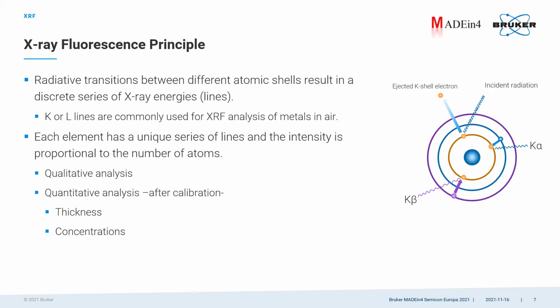This is a brief refresher on what X-ray fluorescence is. So we hit the sample with a primary X-ray beam. By doing this, it's possible that electrons from the inner shells are knocked out, and this will leave a hole in the electron shell, which is then immediately filled by an electron from a higher shell. And this jump creates a photon with a specific energy. Filling this void with an electron from the L shell generates a K alpha photon, and when the electron comes from the M shell, it is a K beta photon. We can measure these photons with an XRF detector.